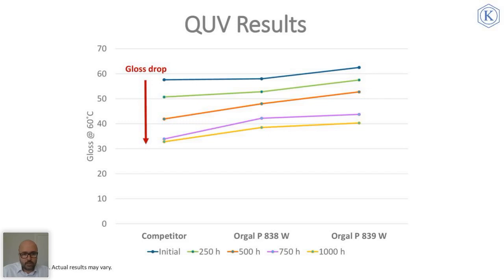So this blue line is indicating the initial gloss of 3 binders in the same formulation. 839W has slightly higher gloss at the beginning, around 62 degree, and it drops to 40 after 1,000 hours. Competition has slightly higher drop, and 838W is also in the similar level of 839.